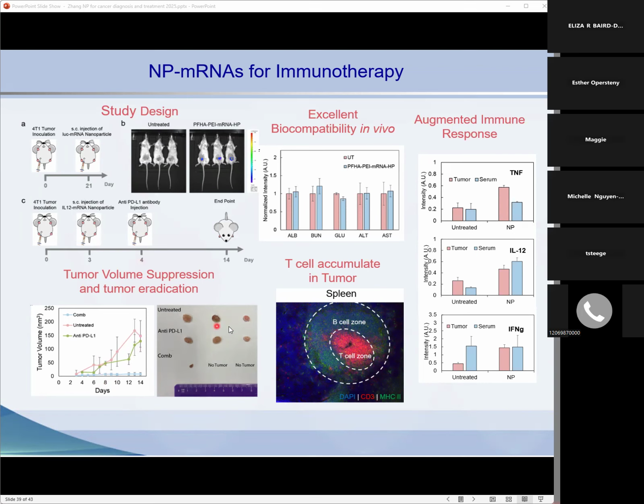With the combination, for example, initially there is a big tumor. Once we inject the nanoparticles, many of them don't show tumor anymore. We also checked whether T cells accumulated in the tumor. Interestingly, a lot of T cells accumulated in the tumor, not in the other regions. Then we studied whether they induce an immune response, so we took blood to see if they release cytokines. We also did biocompatibility studies to make sure the nanoparticles do not have any toxicity or immunogenicity.